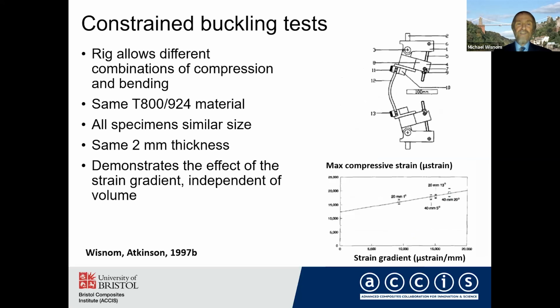In order to overcome that, James Atkinson developed this constrained buckling test rig, where the specimen is clamped and we can adjust the initial angle and the additional offset so that we can get different combinations of compression and bending. These results are with the same T800-924 material as in the previous pin-ended buckling, and all these specimens are a similar sort of size. They're not exactly similar, but they are all the same 2 millimeter thickness. You can see that as the strain gradient increases, the failure strain increases as well. This demonstrates that the effect of the strain gradient is there independent of the volume of the specimen.